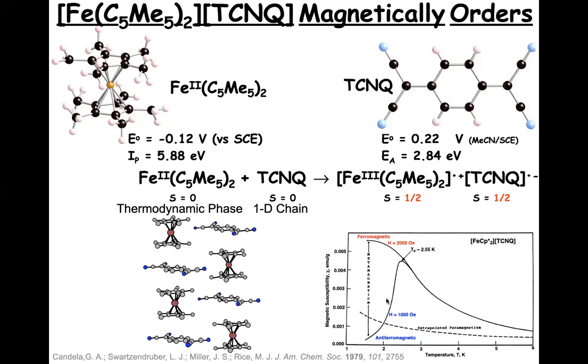Statistically, most things would be antiferromagnetic. But we also measured it at 2,000 Gauss applied field, and when you do it at 2,000 Gauss applied field, it never reaches a maximum. It keeps rising. We've taken it down to about 65 millikelvin, and it never goes down. And it acts as a ferromagnetic material.